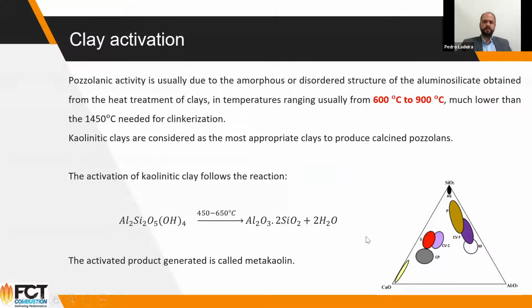As we know, simply we are not talking about too much on calcium anymore. We are more focusing on aluminum silicates, where we want to remove the water content on it and transform it into amorphous but still very reactive material, with fairly low temperatures compared to cement, where we can pull out what we need to activate those pozzolans.